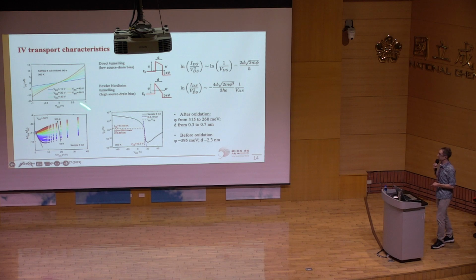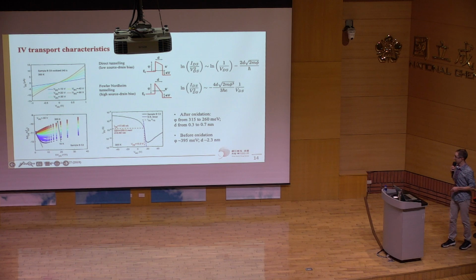If we take exactly the same data and plot it in this form, so your y-axis is the natural log of current divided by bias voltage squared as a function of 1 over the bias voltage, you see this trend here. And we do that because at low temperatures, your current through a tunnel barrier is described by these two equations, depending upon whether you're in the low bias regime or the higher bias, or Fowler-Nordheim, tunneling regime.